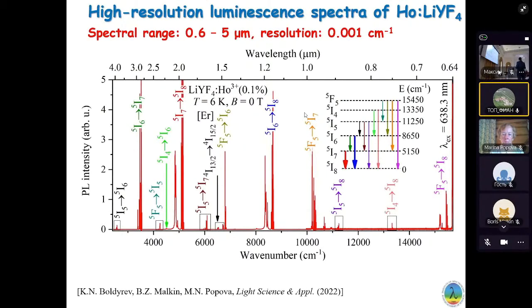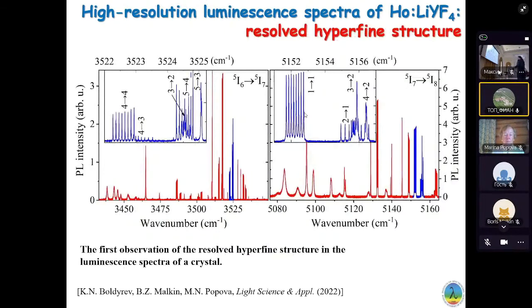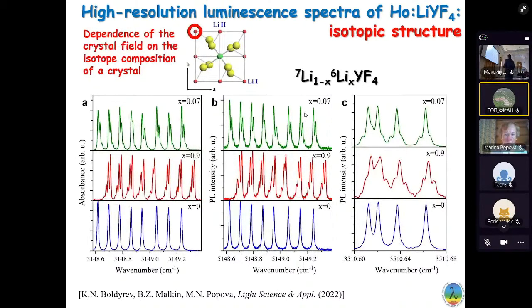Here you can see the high-resolution luminescence spectra of this crystal. There are a lot of transitions, much more than in absorption spectra, because we observe not only transitions to the ground state, but between the excited multiplets. So there is a scheme of our observed spectra. And in these spectra, we, for the first time, observe the resolved hyperfine structure in the luminescence spectra of a crystal. You see really good spectra. As well as for the absorption spectroscopy, we observe the isotopic structure in the luminescence spectra as well.